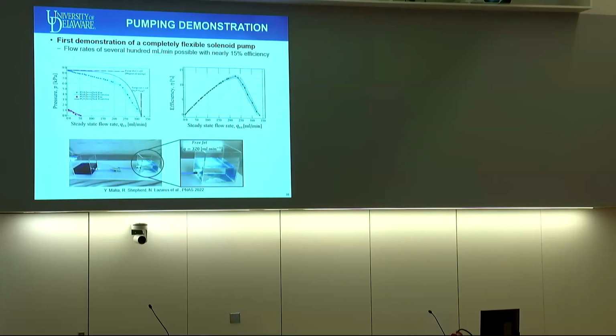And so using this, we're able to demonstrate the first completely flexible solenoid pump. And because this is a much more mature, well-known pumping topology, we're able to get some very high flow rates. This is about 300 milliliters per minute using the soft solenoid pump. And we're able to get reasonable efficiencies for a soft pump. Not as good as a more conventional copper-based pump, but still up to about 15% efficiency using this flexible solenoid pump design.